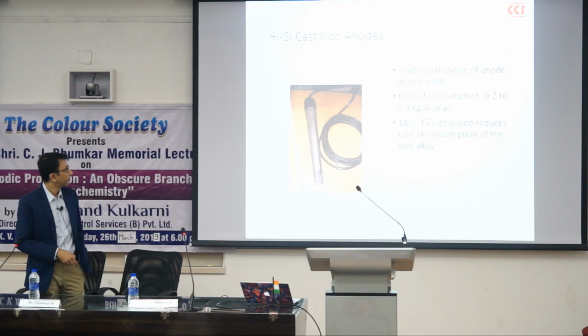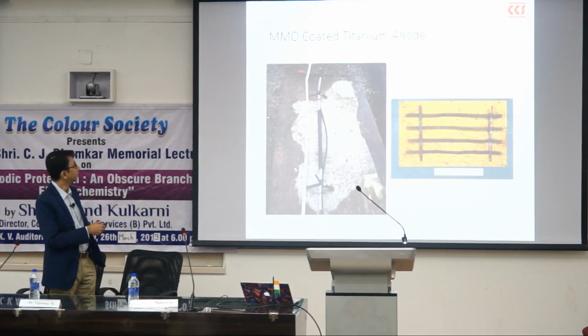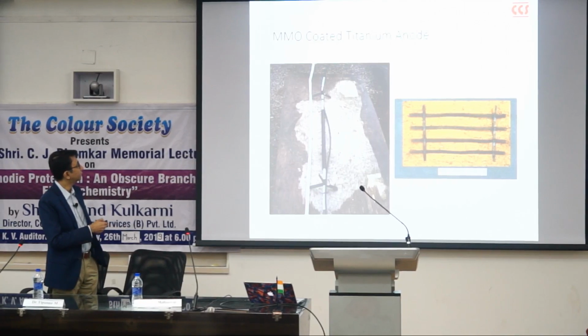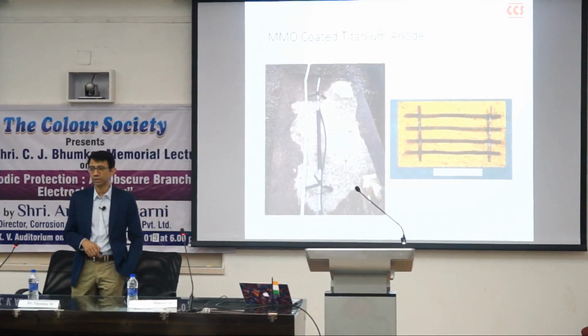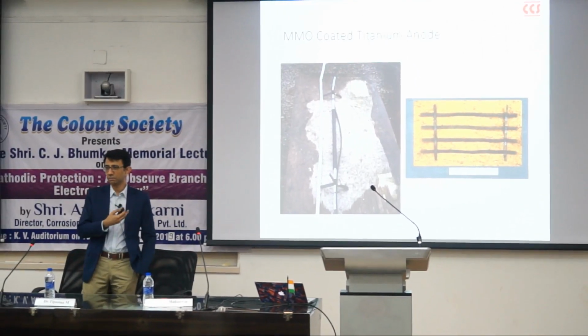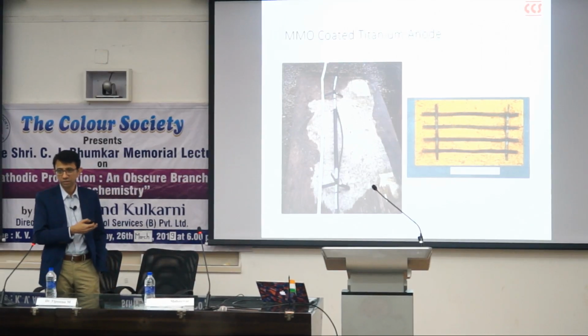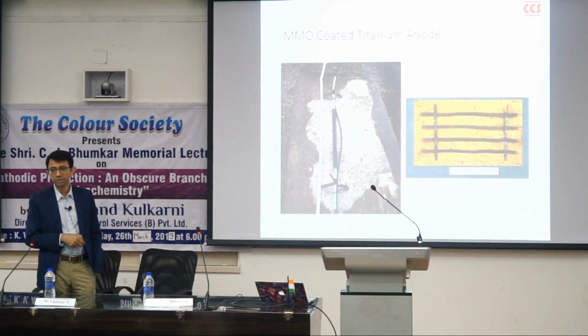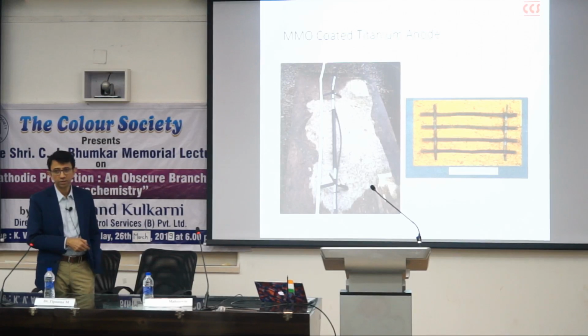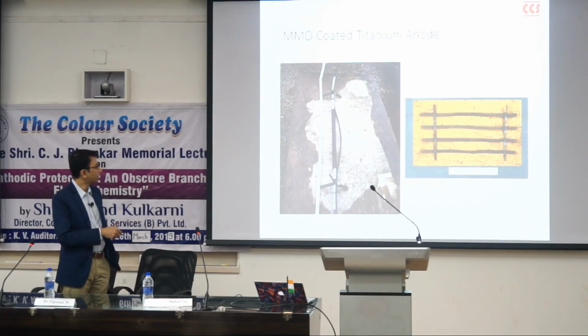80s. And it was in the 90s that they started the use of mixed metal oxide coated titanium anodes. This is just a blend of rare earth oxides that is thermally applied to a titanium substrate, very low consumption rates, 1 milligram, 2 milligrams, 3 milligrams per ampere year. The different kinds of configurations available for pipelines, for tank bottom. This is great for a tank bottom.